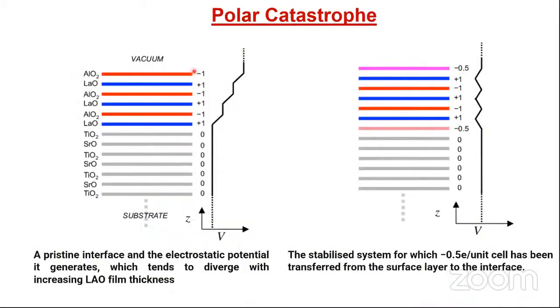And the idea of the formation of the two-dimensional electron gas was that there is a polar catastrophe. This is the idea of polar catastrophe. That is when you have a non-polar substrate like strontium titanate, and on top of that, you grow a material which is polar, like lanthanum aluminate. Then the potential builds up, leading to a potential catastrophe. And this can be avoided. This catastrophe is resolved if half the charge per unit cell from the surface is transferred to the interface. The catastrophe is resolved, and as a consequence, a two-dimensional electron gas is formed at the interface.